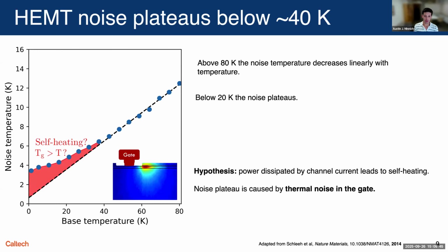And for a long time, there were no really accepted explanations for this. What I did as one of my first efforts in this field was investigate the possibility of self-heating. In this hypothesis, the power dissipated by the bias applied to the device leads to the gate temperature being hotter than the physical temperature. And if that were the case, the gate would emit more thermal noise than you would predict in the simple circuit model, and then you'd get more noise measured than you predicted.